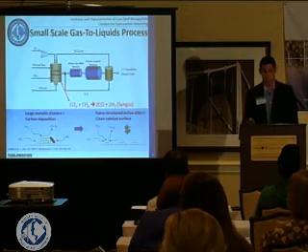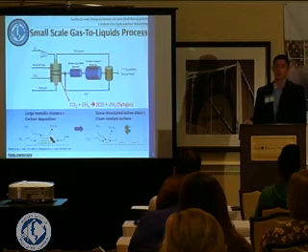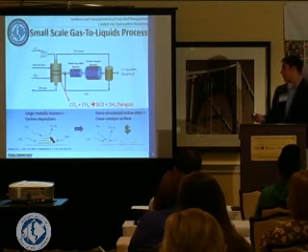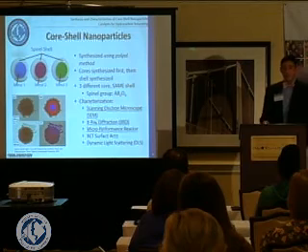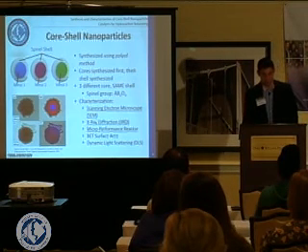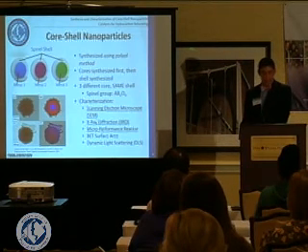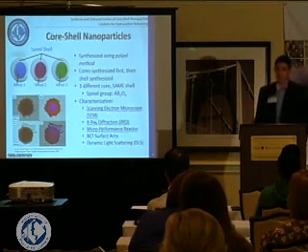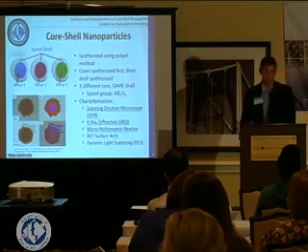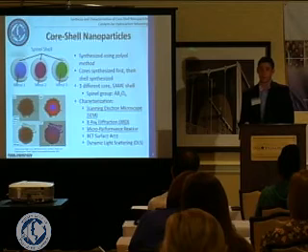The nanoparticles come into this because they are really small and therefore allow small active sites for this reaction to occur, which prevents the buildup of coke or carbon, which would otherwise clog this reformer and render the process useless. So I made 3 core shell nanoparticles. I used the polyol synthesis method, which is a common method in the field. I first synthesized these cores and then put a shell around them. There were 3 different cores I used, but I used the same spinel shell on each of them.